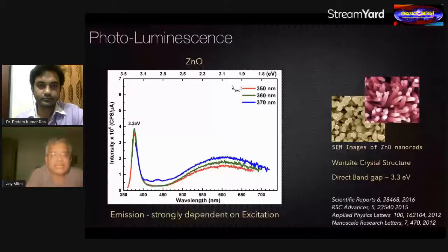When the light comes out, it's of a very different wavelength. The peak wavelength is somewhere around 370, 380 nanometer. As Stokes said, it will always be red shifted, that is, at a longer wavelength. And then there is a huge, very shallow bump covering the entirety of the visible spectrum.